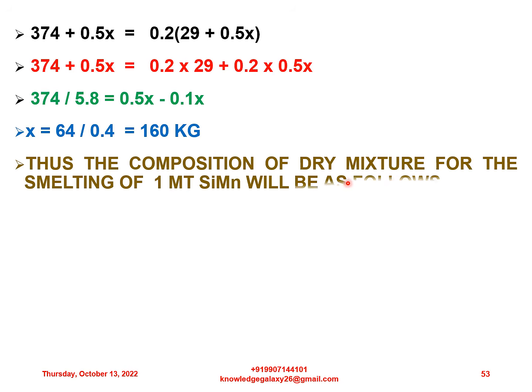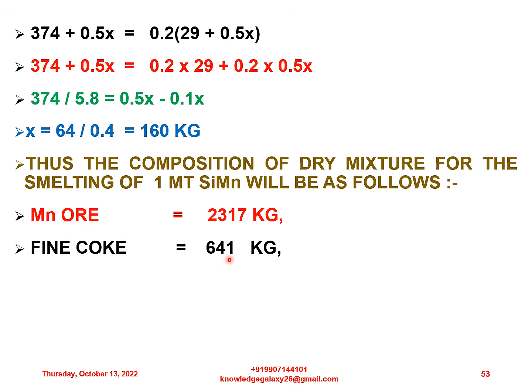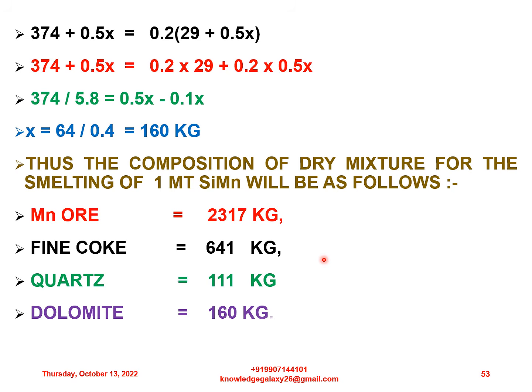Thus, the composition of dry mixture for the smelting of 1 metric ton of silicomanganese will be as follows. So we have calculated all the quantities. Manganese ore 2317 kg, fine coke 641 kg, quartz 111 kg, and dolomite 160 kg. I hope this calculation is very clear to you all, and I have covered all the calculations of each element very precisely, so you can learn the burden calculation very accurately and precisely.